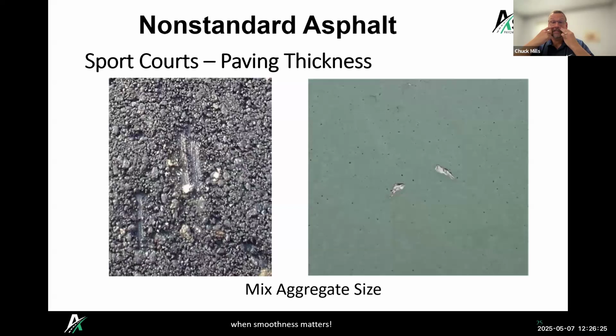Another issue that can happen is selecting a mix that has larger aggregates in it, and then not selecting a thick enough paving course. So paving thickness is important. When we talk about paving thickness, we want to have a minimum thickness of 3 times our nominal max aggregate size in our mix. So, if we're trying to pave like a 13A mix at 1.5 inches, you can start dragging stones and things like that, and that can cause issues in the future after we've coated that, where you get stones popping out and things, and cause some scars there.